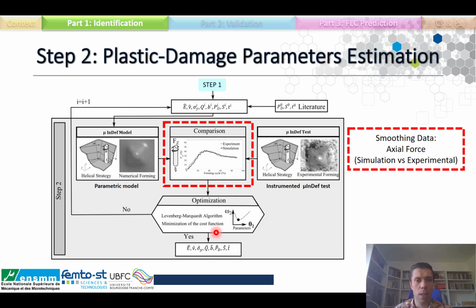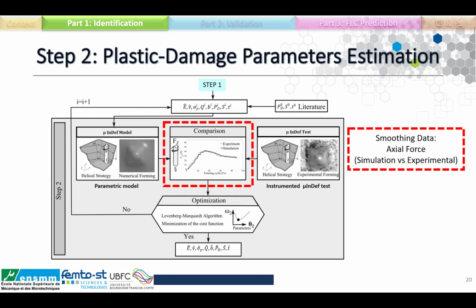To make it simple, we have the forming forces from the numerical simulation. We have the forming forces from the experimental test. So we compare both, and using the optimization toolbox, we are looking for the least difference between the experimental and the simulation forces. When this is achieved, we have the final set of material parameter values. The identification procedure computing time is quite big. We use a cluster computer with between 16 and 20 processors, and the whole calculation takes around 5 days.